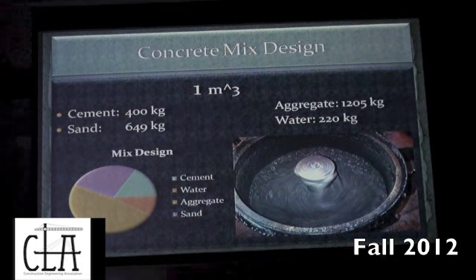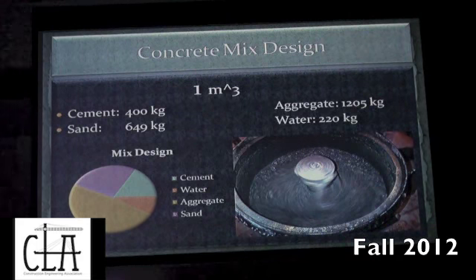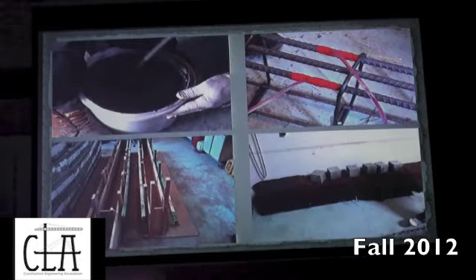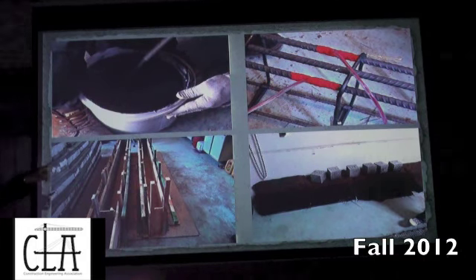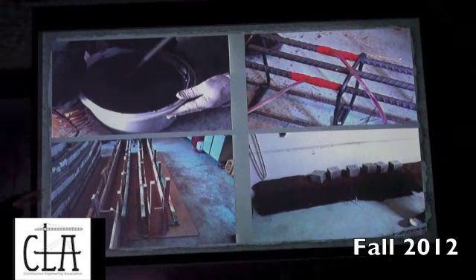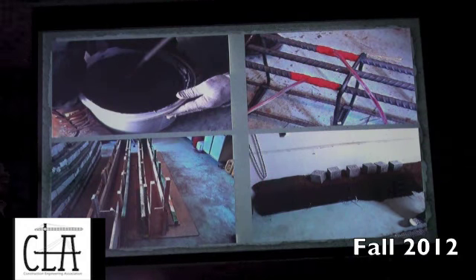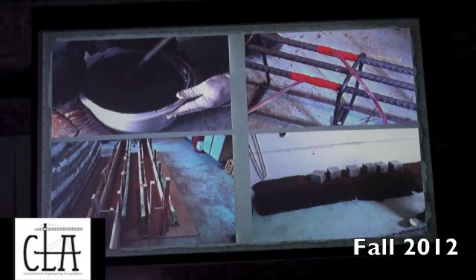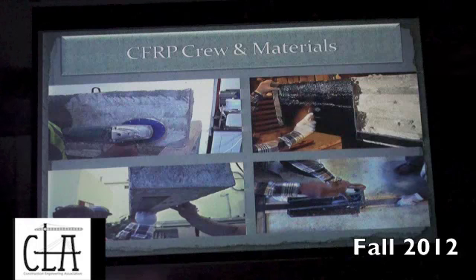This is our mix design for the 10 beams: cement 400 kilos per cubic meter, sand 649, aggregates 1205, and water 220. These are some pictures from the lab: mixing the epoxy, how we attached the strain gauges to the steel, our formworks, and how we cured our beams and cubes. Because we have full-size beams, we didn't have a curing room big enough.